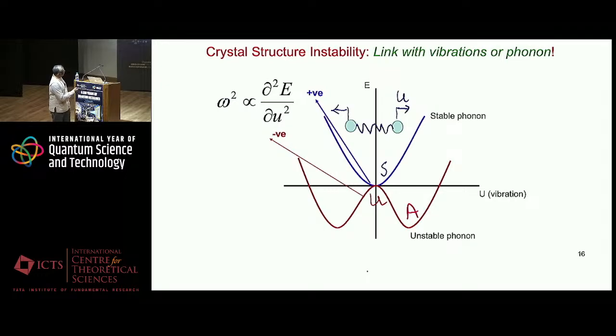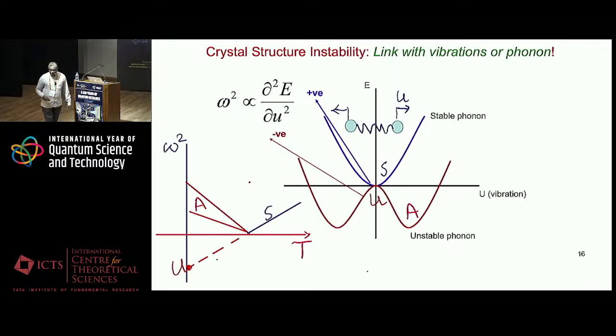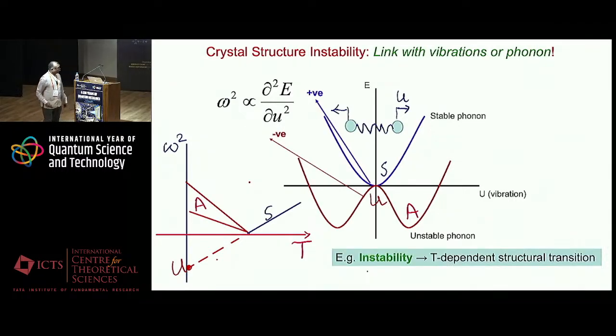So the crystal instability is determined by whether the vibrational frequency, which is the second derivative of energy with respect to vibrational amplitude, is positive or negative. If it's negative, it's an unstable vibrational mode. And in a structural phase transition, the high symmetry phase, which is stable only at high temperatures, is unstable. And if you extrapolate the frequency down, this is where the phonon becomes soft, as observed by Raman, and later also introduced by Cochran and Anderson. And this unstable mode defines the instability of the high symmetry phase. And that is what governs the temperature-dependent structural transition.